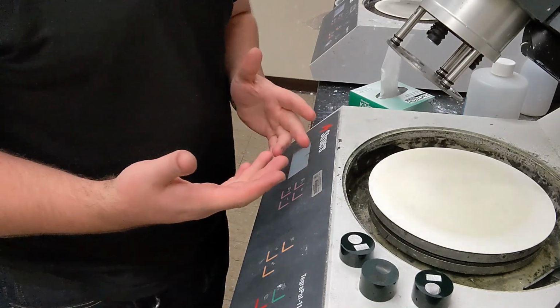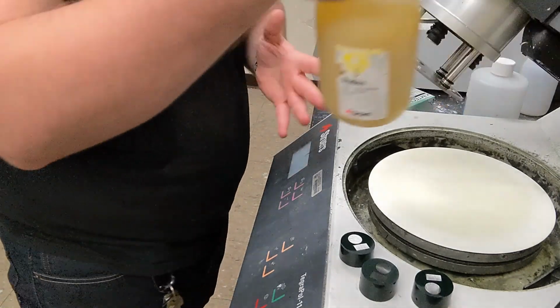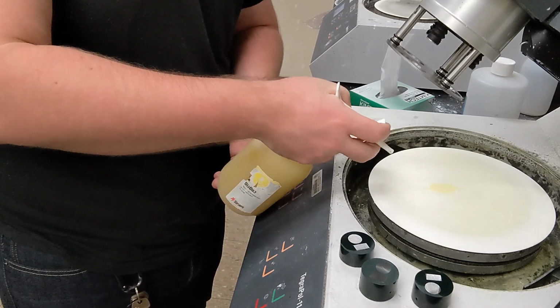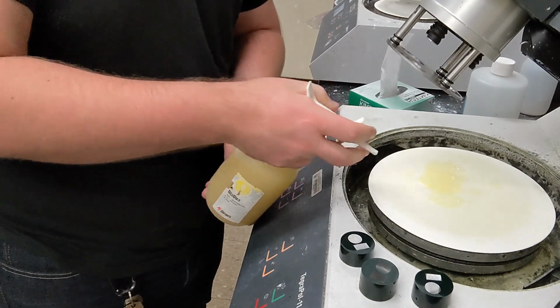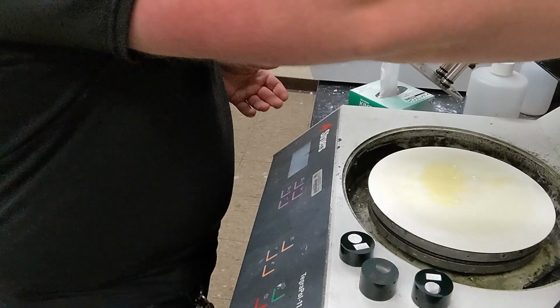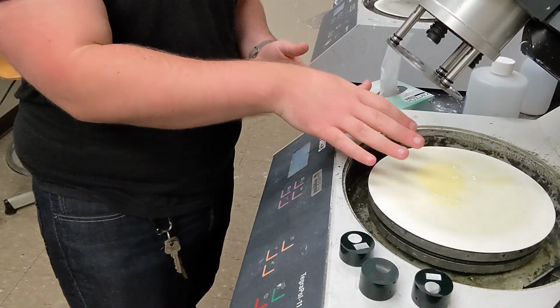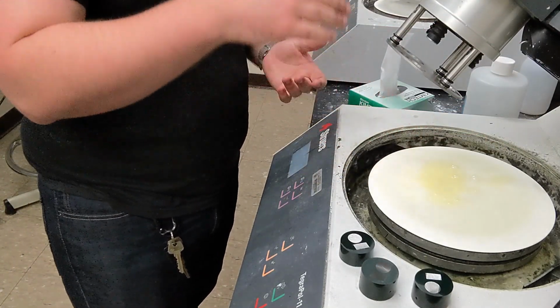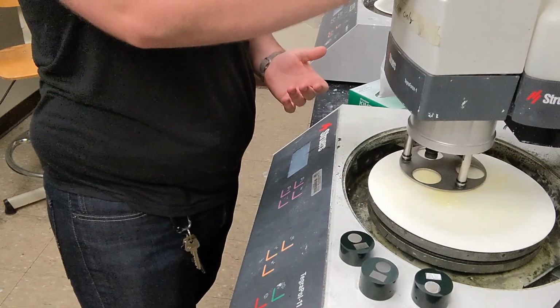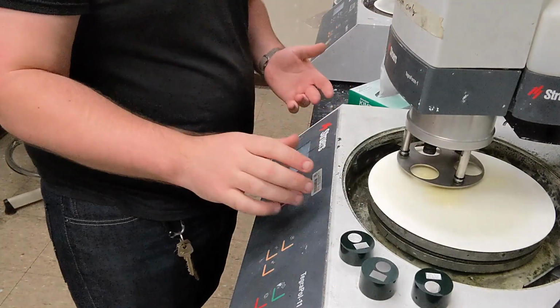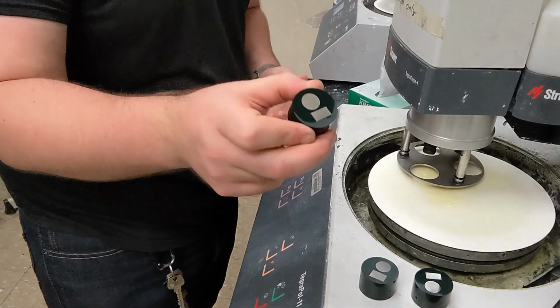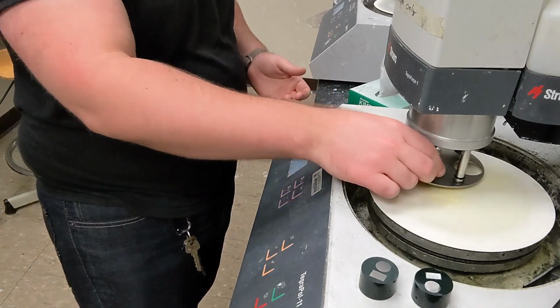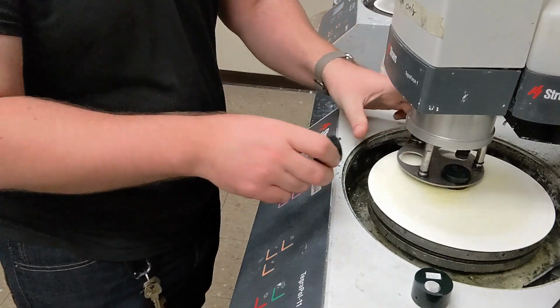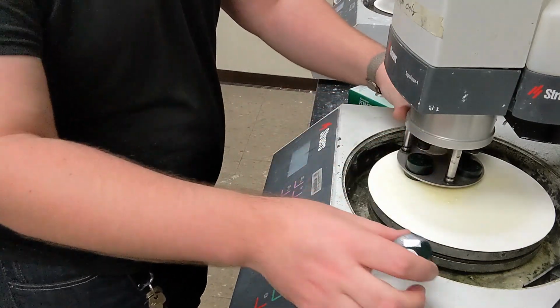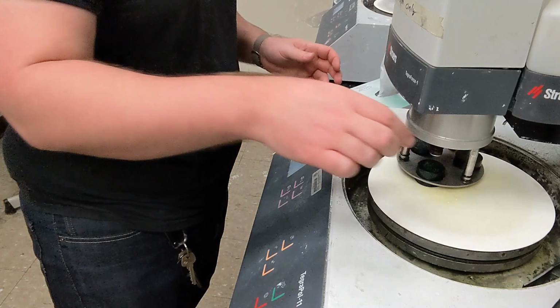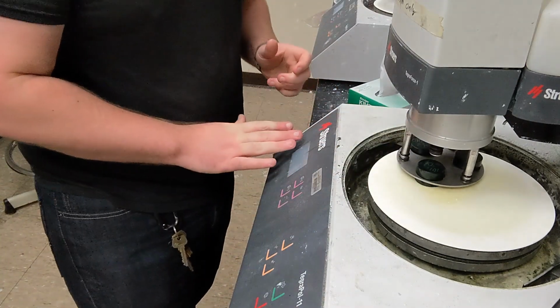So the way that we run test is we take our solution, we spray about 5, we'll say 6 very, very tiny splashes of our diamond suspension. This guy we bring down, it clicks into place. We then take your 3 samples, we place them face down in the machine. We have 3 groups, we have 3 samples, we have 3 holes. It works out perfectly. On the machine, there's a few settings.